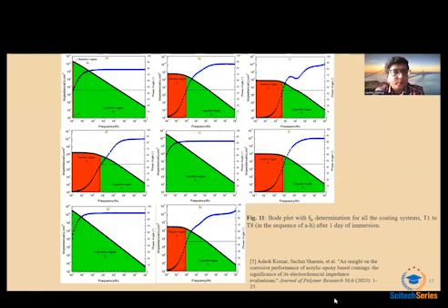So these are the breakpoint frequency graphs to support the results, and we can see that there are two regions in figure 11. We have the red one, which is the resistive, and the green one, which is the capacitive. So this breakpoint frequency actually indicates that a majority capacitive region means that the coating is intact, and it also provides excellent barrier protection performance against the corrosion. Okay, so we can see the samples T1 to T8 in the sequence of A to H, and we can see that for E, figure 11E, which illustrated the T5 sample, and of course figure G, which illustrated the T7 sample, and T1, which is A, so T1, T5, and T7, A, E, G, illustrated a complete or almost complete capacitive region, which were in line with the results demonstrated in the EIS over a period of 60 days.